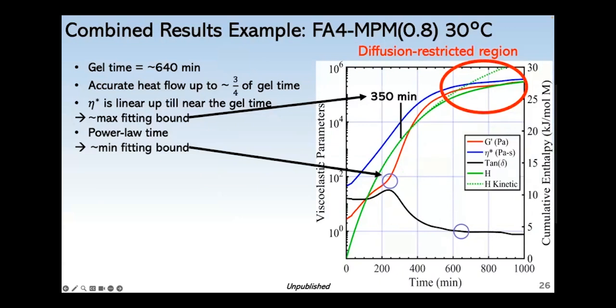And on this slide, I wanted to just show you an example of the combined results for the rheology and microcalorimetry. This sample, FA4-MPM(0.8) 30C, gels at 640 minutes. And in the plot, I'm showing the viscoelastic parameters on the left. So G prime in red, complex viscosity in blue, and the tan delta in black. And on the right side of the plot, I'm showing the enthalpy.